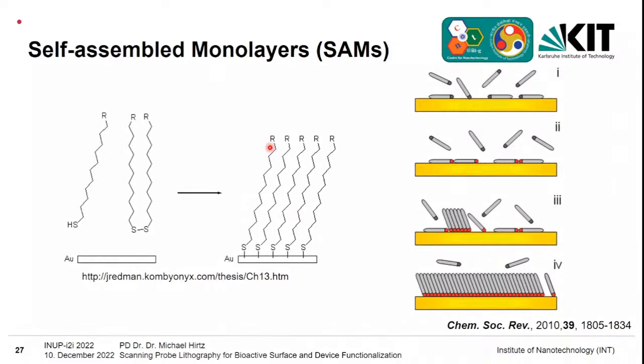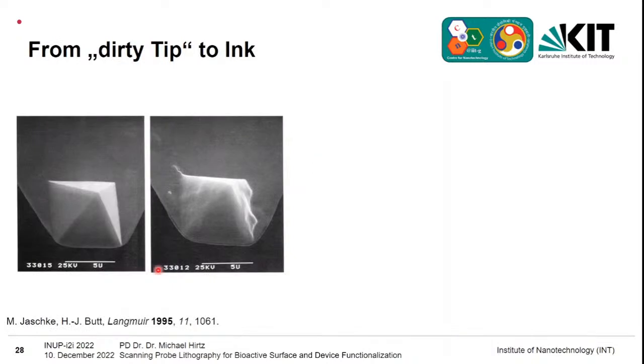And this led to a lot of interest in self-assembled monolayers, and they were also frequently imaged with AFMs. And this led, in the late 90s, to the observation that if you scan such a monolayer, then sometimes at the end you end up with material from the monolayer attaching to your tip. So a clean AFM tip maybe looks like this. You can see very neat, everything is tidy. And afterwards it can be covered in such thiol material because it's just attaching to the outside of the tip.